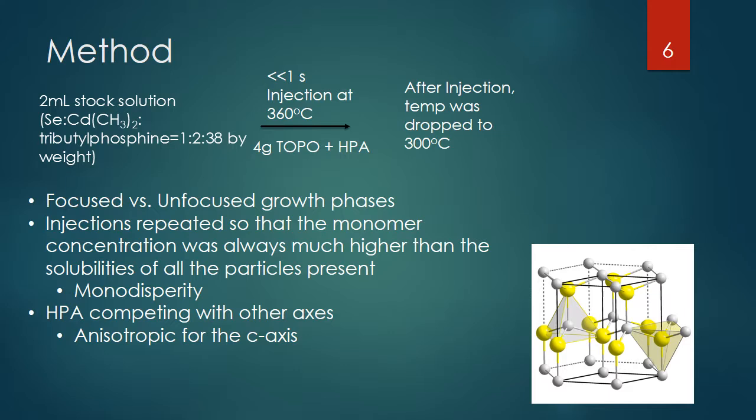This nucleation phase is basically where the cadmium selenide nanoparticles were created and synthesized at the very beginning. Then, after less than a second, the temperature was dropped down. This drop in temperature was basically to switch from nucleating new cadmium selenide particles to just growing the ones that are already there — switching from the nucleation phase to the growth phase.